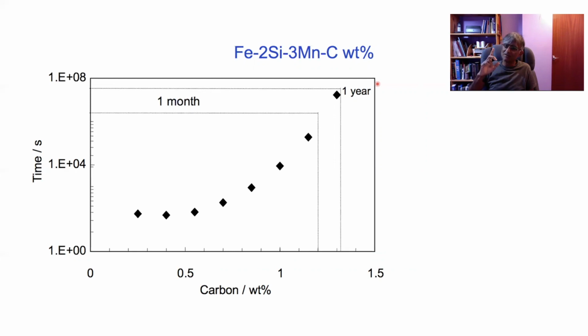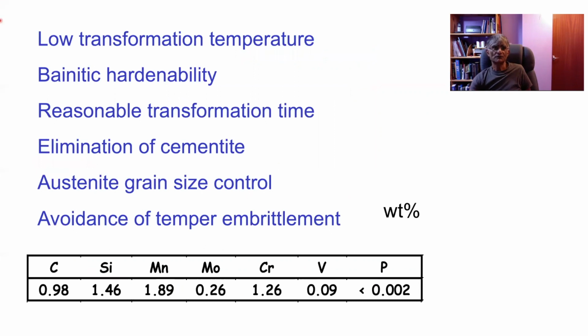But unfortunately, we don't have that patience. So we make an alloy which will transform in about 10 days of isothermal heat treatment at about 200 degrees centigrade. So we've achieved the low transformation temperature by having a carbon concentration of 1 weight percent. This is to suppress the cementite, hardenability.